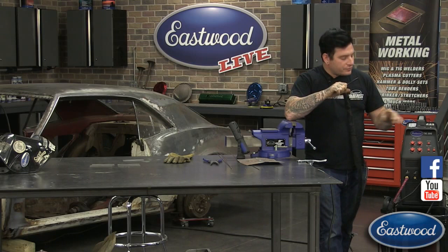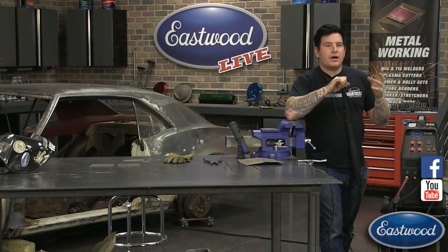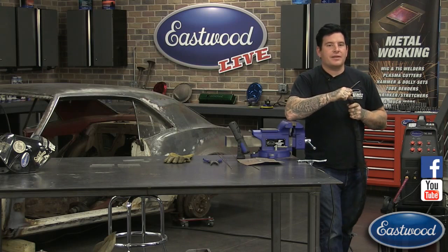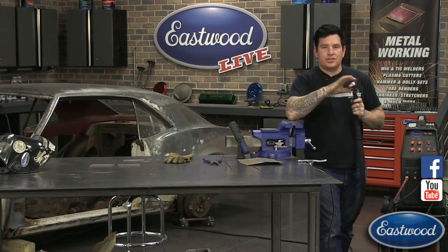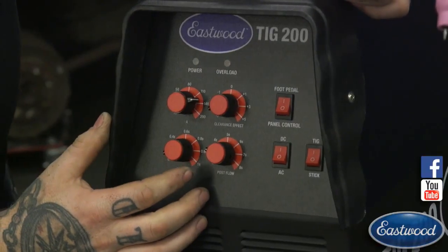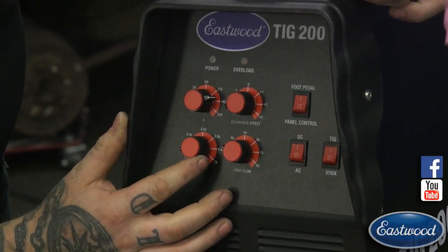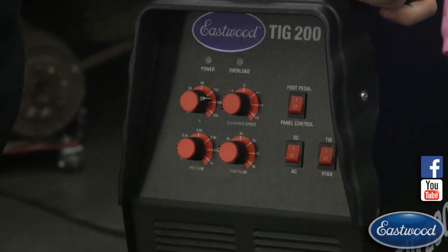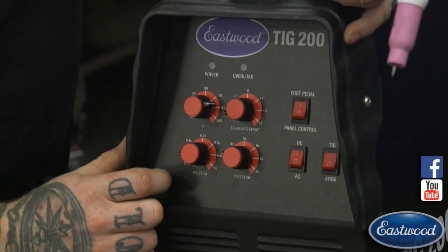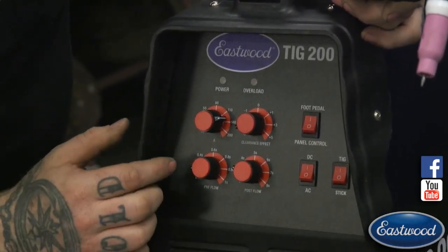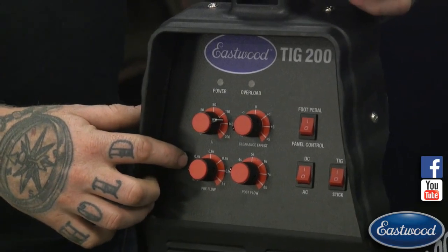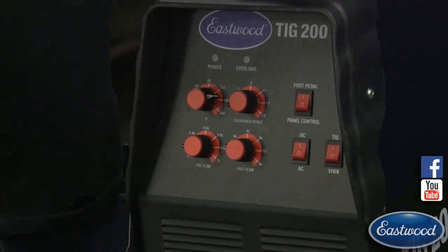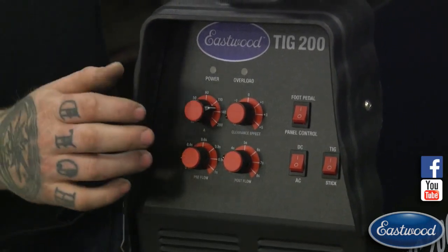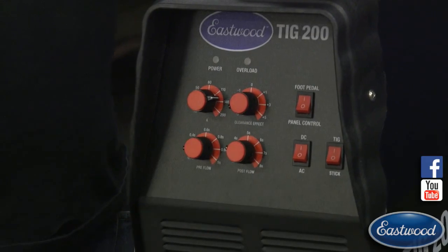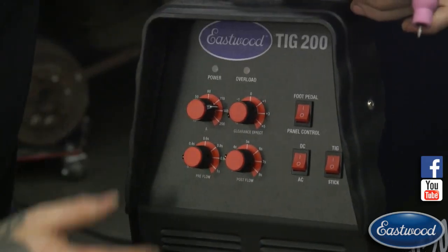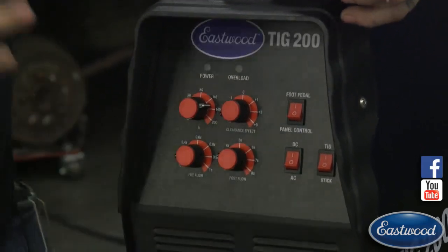If you don't have that pre-flow, you could have a little bit of pitting or some contaminants that can get in the weld for that split second before the shielding gas comes out. So that's why you need that. The dial I keep fairly low most times. I usually keep it around two, just a little under 0.2 seconds. So it's a fraction of a second, not a full second. Sometimes if I'm doing something in aluminum, or if I'm in a joint where I have my stick out on my tungsten a little further, I may turn that up a little higher so that I get a little bit of extra time of shielding gas to get in our weld area.